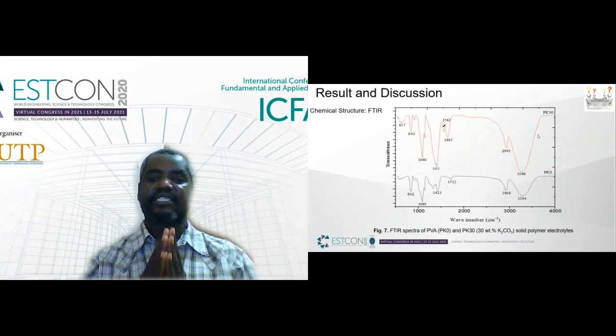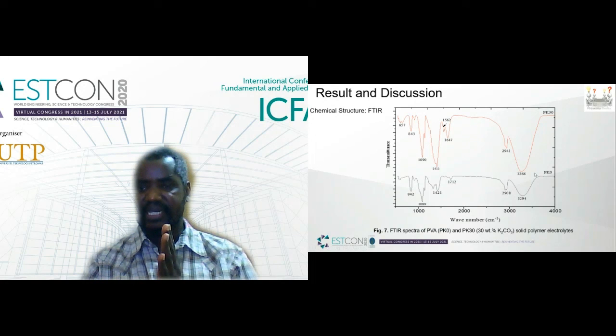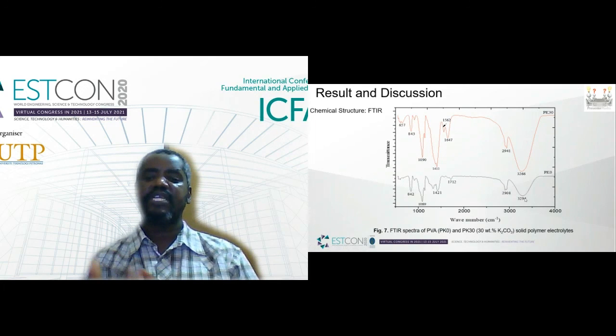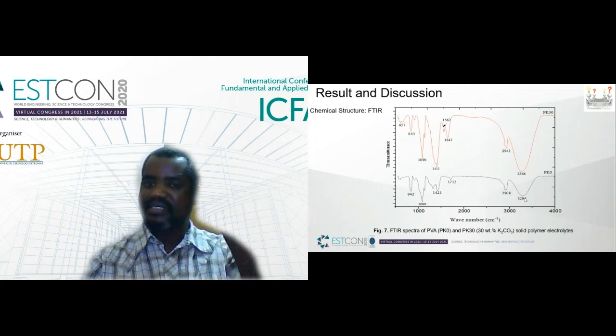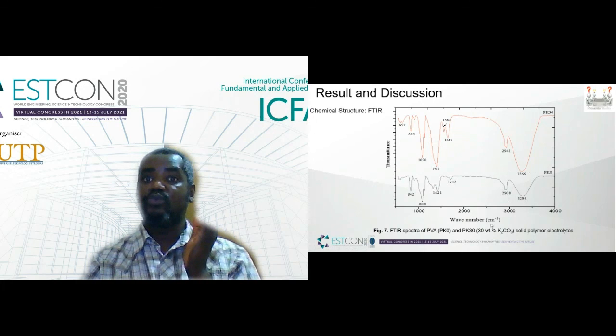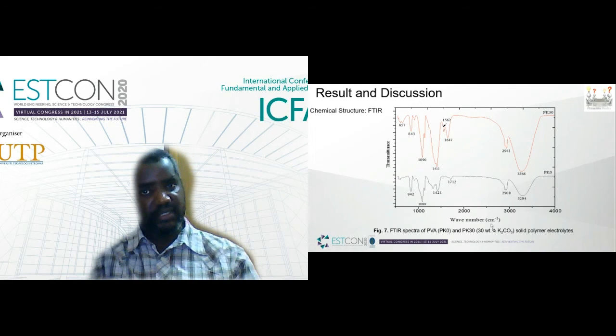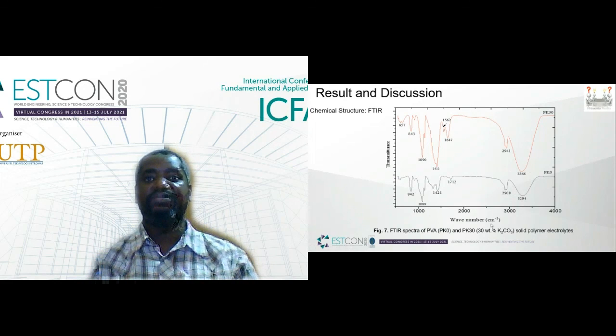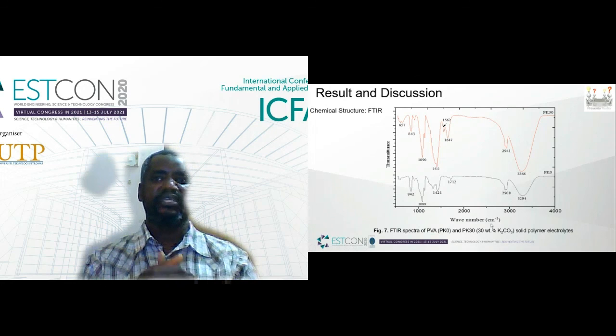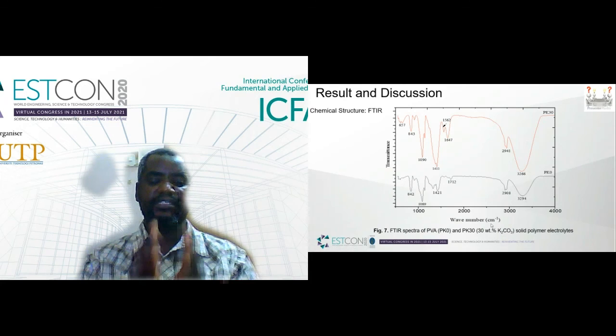Here, as can be seen, the spectrum of the pure PVA and potassium carbonate is shown in this particular figure. This result shows that the hydroxyl band of PVA is seen around 3294 per centimeter. However, after the successful incorporation of the potassium carbonate, the band has shifted from 3294 to 3266 per centimeter, reflecting the physical connection between the polymer and the salt, which is due to the mix of ions in the polymer matrix.